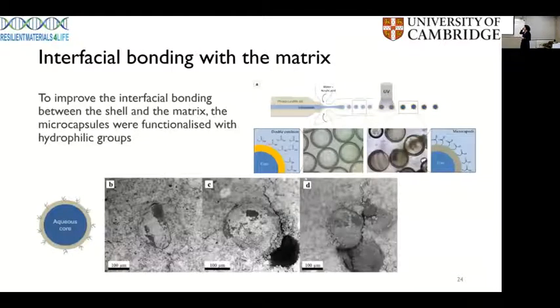Using microfluidics, there is also the chance of functionalizing the shell. It's not only for microfluidics, but it's a process that very often you have to do when we're talking about microcapsules. Because not necessarily there will be a good interfacial bond between the capsule and the cementitious matrix, or you want to increase the stability of the microcapsules. And one way of doing this is by investigating the functionalization of the shell with hydrophilic groups. So there are groups that are going to bond better with the cementitious matrix.